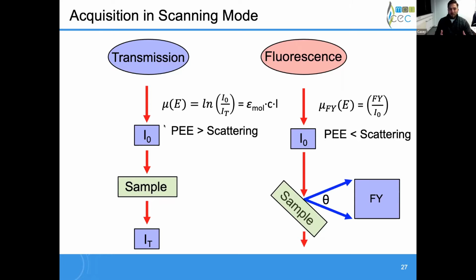There are two predominant ways that most of us, from a practical standpoint, go about recording hard X-ray spectra. The classic way is transmission, which follows the Lambert-Beer law, and it's very effective when your absorber is very concentrated and absorbs a lot of radiation compared to your scatterer. On the other hand, fluorescence tends to be a lot more advantageous when scattering is a major factor and your absorber is at very low concentrations. In this case, we have some sort of detector or analyzer which collects photons over a given solid angle theta, and our signal is proportional to the fluorescence yield over I0.